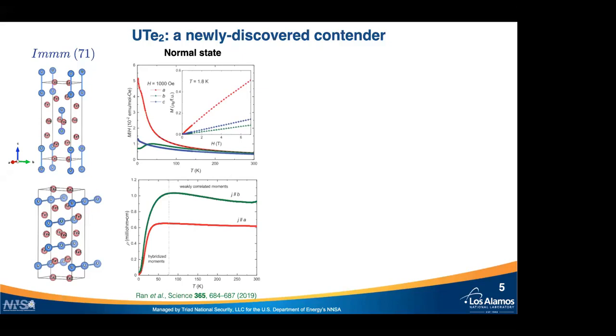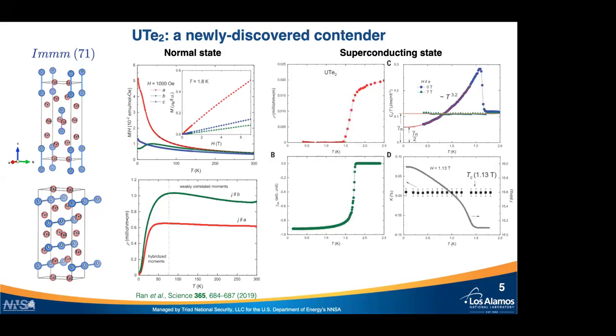Here's the electrical resistivity. At high temperatures, we can think of the system as an incoherent system of f-electrons, weakly correlated moments, but at low temperatures, hybridization sets in, and the system has a very low resistance until it goes to a zero resistance state. But a superconductor is also characterized by the Meissner effect. So panel B here has also the diamagnetic signal below about 1.6, 1.7 Kelvin.